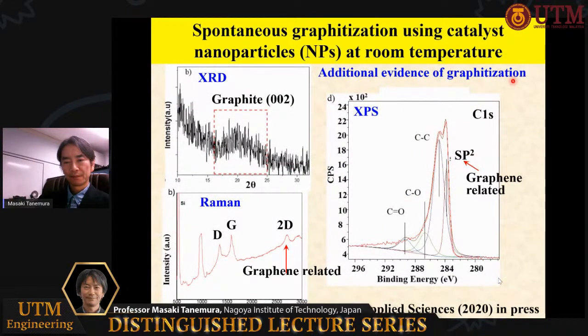These are macroscopic evidence of the graphitization for the as-deposited film. By XRD and Raman analysis, we confirmed the graphite-related peaks, and in the chemical bonding analysis by X-ray photoelectron spectroscopy, XPS, we observed the graphene-related sp2 peak here.